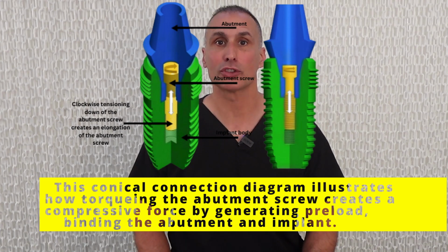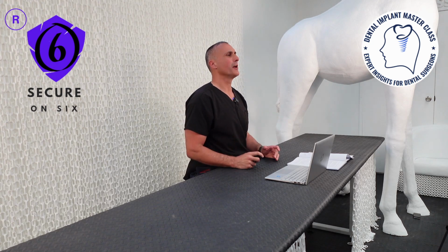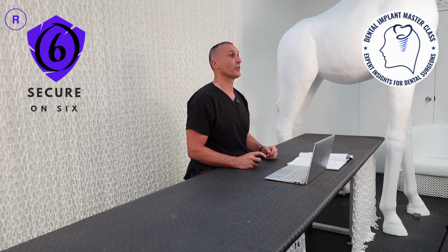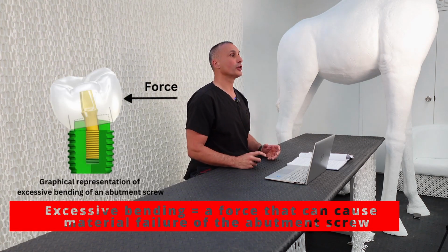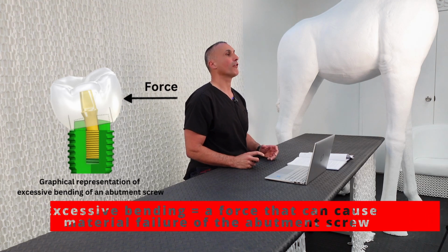The elastic recovery of the screw generates the clamping force, ultimately pulling the prosthesis and the implant together. To maintain the stability of screw joints and prevent separation, it is essential to preserve preload and minimize fluctuations. Several factors, including settling effect, preload, and screw geometry, play a critical role in ensuring the stability of the screw joint. Implant interface design and the precision fit of the mating components contribute to the resistance against mastication forces. Two primary mechanisms of screw loosening for implant-supported restorations are excessive bending of the screw joint and the settling effect.